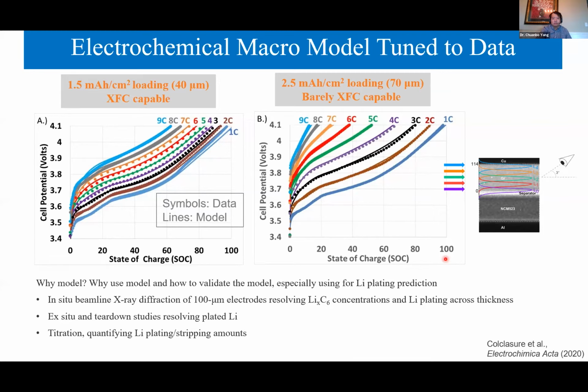The electrochemical model has been used as feedback to experiments and provides guidance on cell design requirements to improve fast charging acceptance at 4C to 6C constant current charging and suppress plating for cells incorporating loading beyond 3 milliamp hour per centimeter square. The electrochemical model has been validated for low loading and moderate loading cells based on the experiments to date, predicting fast charging limitations such as electrolyte depletion and onset of plating reasonably. Model is also compared well with some recent 1C rate operando XRD measurement from Argonne National Lab.